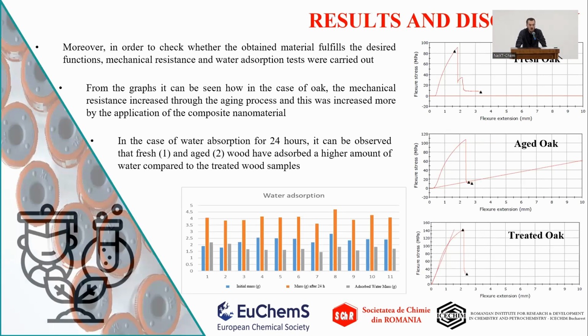Moreover, in order to check whether the obtained material fulfills the desired function, mechanical resistance and water absorption tests were carried out. From the graphs on the right side of the slide, it can be seen how in the case of oak, the mechanical resistance increased through the aging process, and this was increased more by application of the composite nanomaterial.